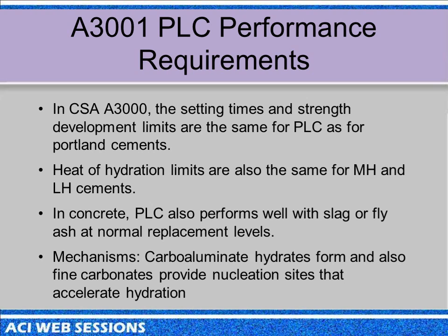And I mentioned the nucleation sites. The other thing that happens is you can form carboaluminate hydrates. We're seeing increased carboaluminate hydrates from the reaction of the carbonate fines with aluminate phases in the cement, like the C3A. And when you start adding things like slag and fly ash or metakaolin to the system, which have aluminates, you increase the potential for more carboaluminate formation. And that fills in space and creates strength as well.